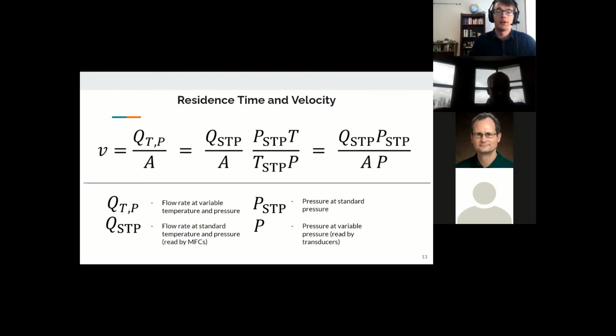The factor with the largest effect on nanocrystal sizes is the residence time. The residence time is defined as the amount of time that gas flows through the plasma, and it's inversely proportional to the velocity of the gas, which is shown in this equation. Just from elementary physics, velocity V is equal to distance divided by time. So time is inversely proportional to velocity. So this is the equation for velocity flowing through the reactor, which gives V in terms of Q_TP, which is the flow of the gas adjusted for temperature and pressure. And to adjust for the non-standard pressure, you have to add this term right here to this equation to get it in terms of standard temperature and pressure, where Q_STP is the flow read by the mass flow controller.